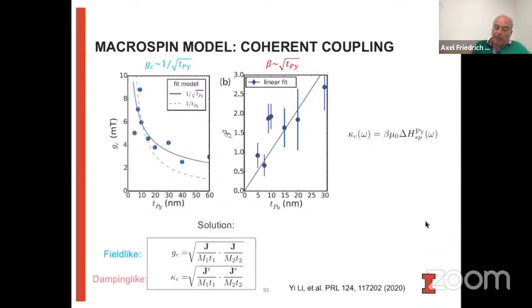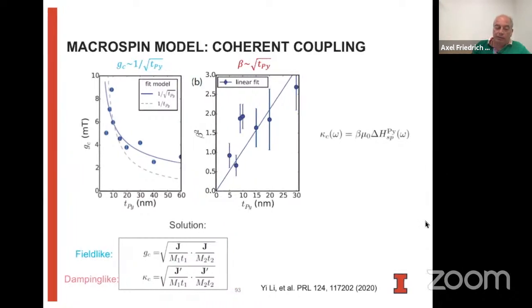Vice versa, we can express the imaginary part of this coupling constant in terms of this parameter beta, which takes account of the frequency dependence of the line width changes that we have. So it's a little bit easier to analyze than this parameter, which has an explicit frequency dependence. And when we plot beta squared versus the thickness of the permalloy, again we get roughly the behavior that we expect. The data here is much noisier than there, but overall it's in good agreement with what we expect from this theoretical modeling.